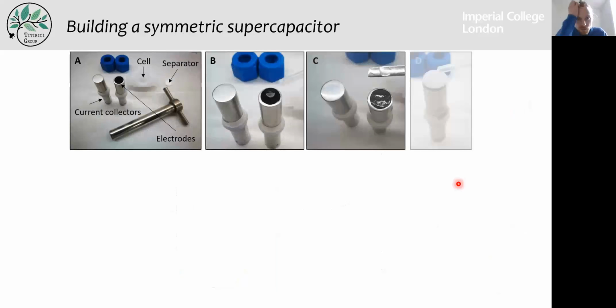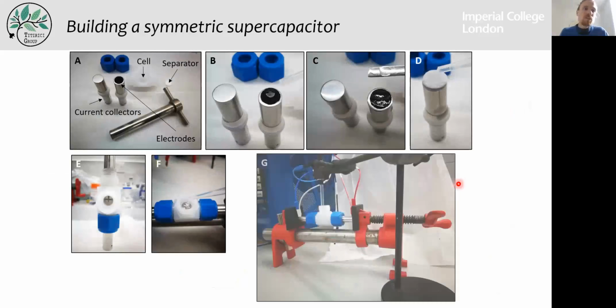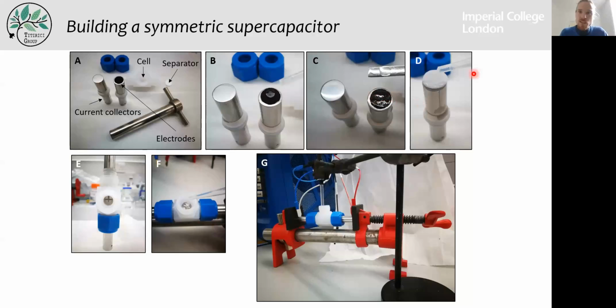So this is how we build our symmetric supercapacitors. We have here our current collectors. We build it, this is called a Swagelok cell. And on these current collectors, we put our carbon electrode here, we infiltrate it with electrolyte, we put a glass fiber separator, and we close the cell. We put the connections directly to the potentiostat, and in the center, we have a reference electrode that enables us to basically watch independently the potential of both electrodes.